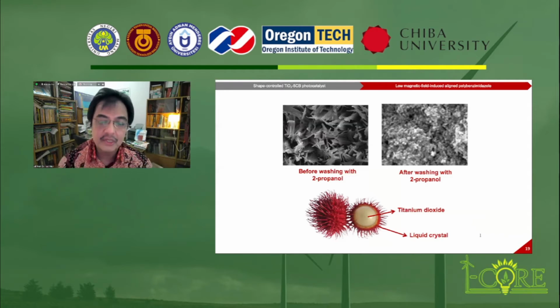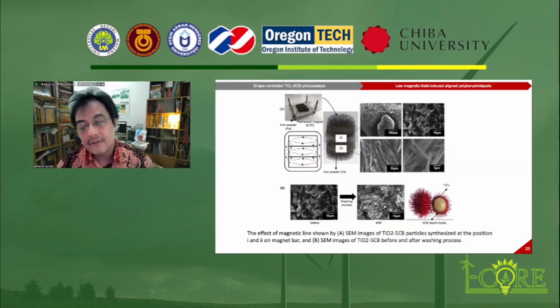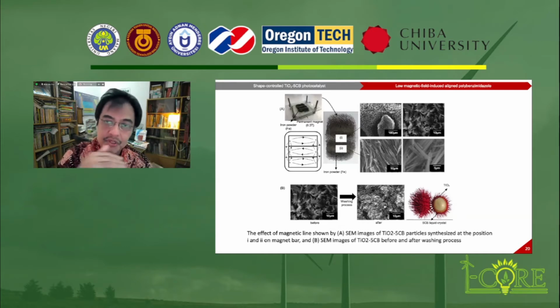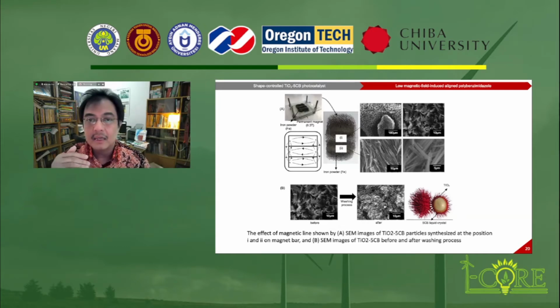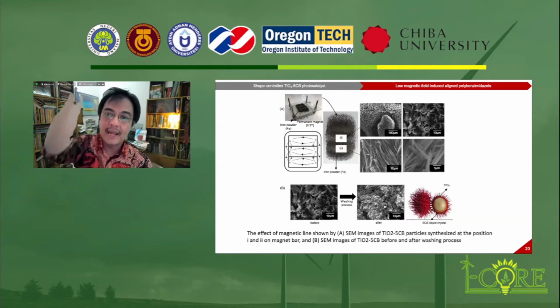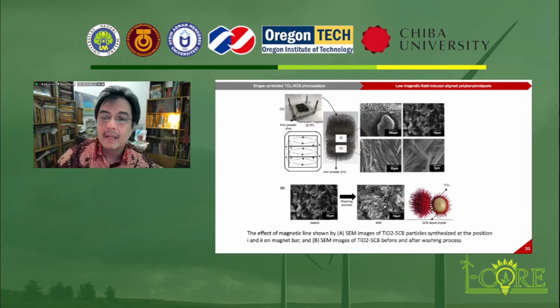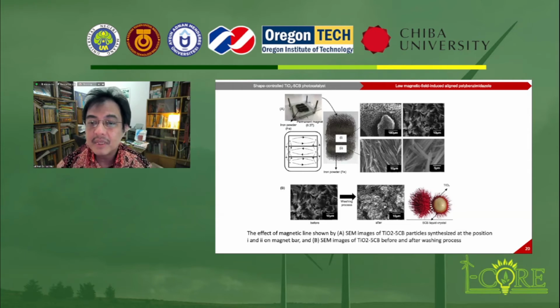This is an illustration of the effect of magnetic line shown by SEM images of titanium dioxide 5CB particles synthesized at different positions of the magnet bar. We put the sample at different positions where the magnet direction is through-plane or in-plane. And this is the SEM image of titanium dioxide 5CB before and after the washing process.